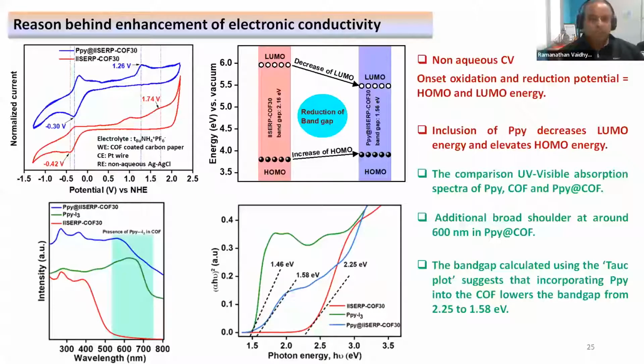Now, what is happening at the electronic level? From the cyclic voltammetry comparisons between the neat COF, which is the red one, and the blue one, which is the polypyrrole loaded COF, we can see the shift in the oxidation onset as well as the reduction onset. The shift can be directly related to the HOMO-LUMO energy levels of these materials. You can see the LUMO level is decreasing and the HOMO level is increasing when we load the polypyrrole into the COF, and the band gap shows a significant decrease from 2.16 electron volts down to 1.58